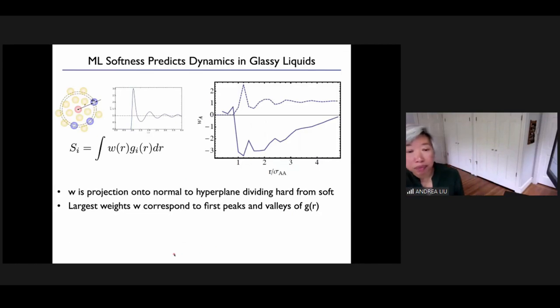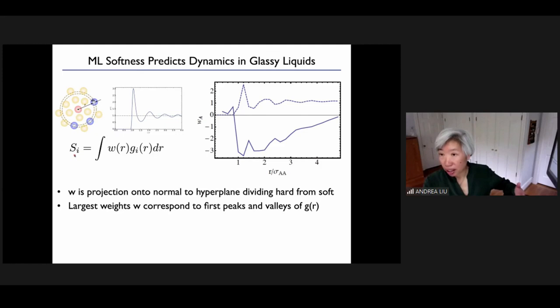Well, previously in my group, we developed this quantity, which we call softness, not a great name, but I apologize for it. But the idea of softness is it is a weighted average of the local pair correlation function of a particle. Okay, so the softness is associated with each particle. Okay, and if I calculate the local pair correlation and weight it by some weighting, which is the same for every particle, the idea is to use machine learning to infer this weighting function, in order for the softness variable to have a very strong correlation with whether the particle will rearrange or not, okay?